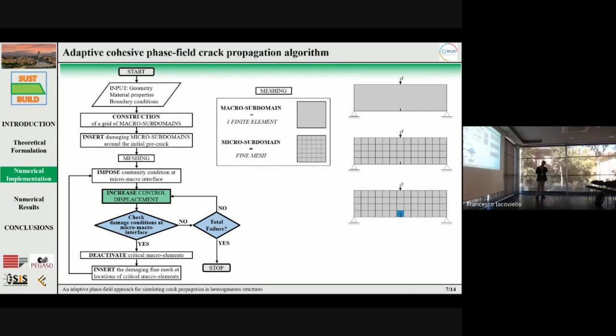The macro subdomains are meshed with a single finite element, while the micro subdomains are discretized using a fine mesh. After that, the analysis starts by increasing the control displacement, and for each increment, the code checks the damage condition at the micro-macro interface.